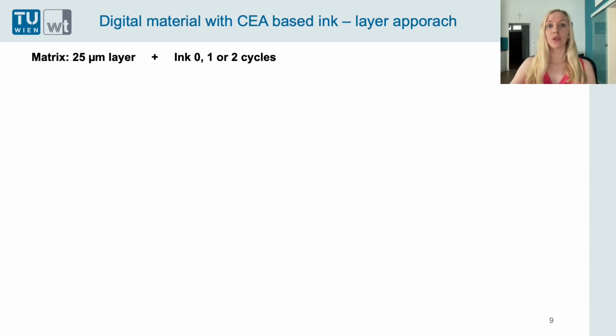Then we use the cyanoethyl acrylate based ink to print a digital material. Here a matrix material was chosen and 25 micrometer layers were printed, and then 0, 1 or 2 inkjet cycles were applied. So 0 means there is no ink and this is only the matrix material as reference, and then 2 different amounts of ink were added.